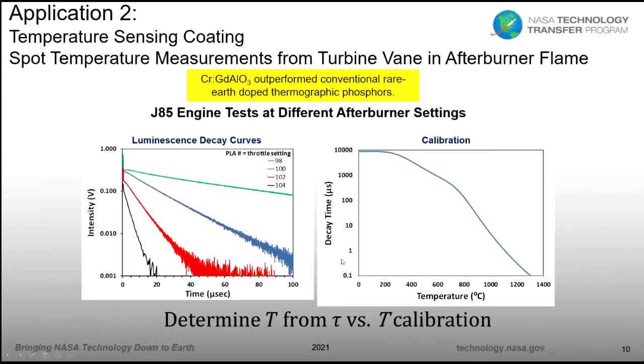Okay, so here are some of the actual measurements. Here you see some of the decay curves from that emission from that spot on the vane as we change the throttle setting. This PLA simply means power lever angle. You have a control, like one that would be in a cockpit, where the angle of that lever goes from 90 degrees up higher, and so this is just the angle of that lever. It's that simple. And you can see how, again, the decay gets faster and faster as you increase the temperature. The decay time is essentially related to the slopes of these, plotted logarithmically.